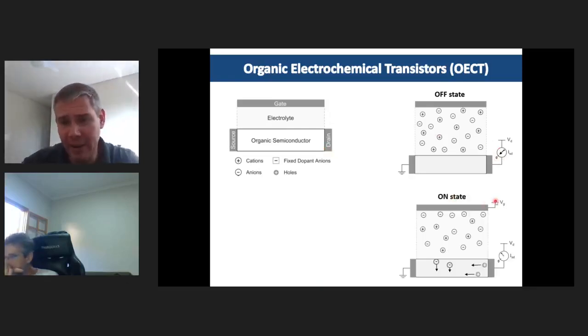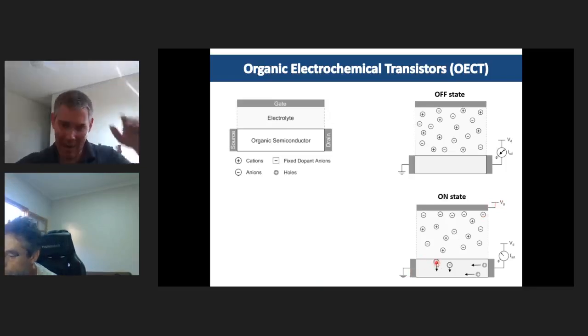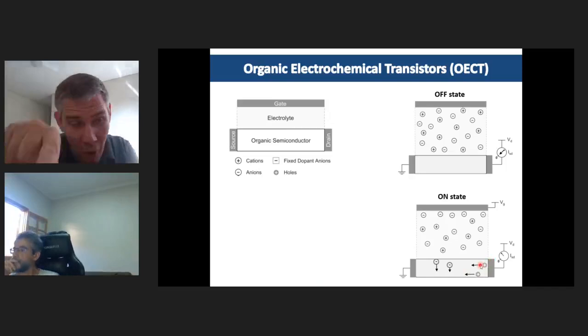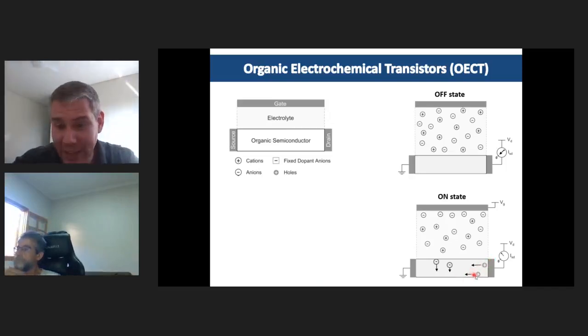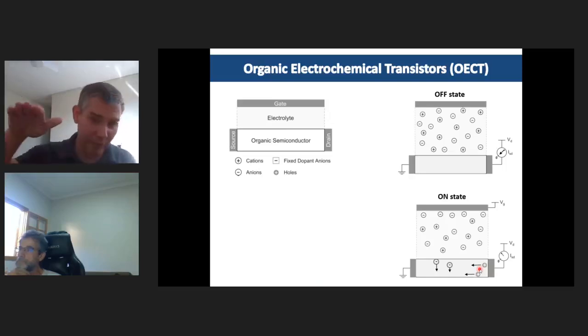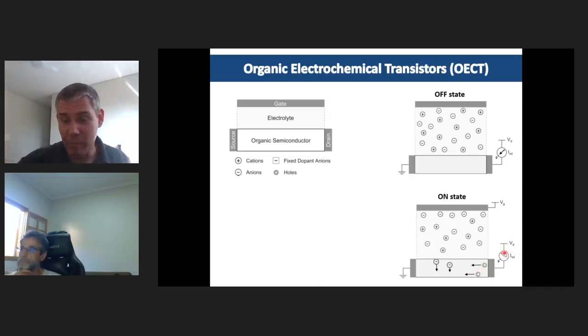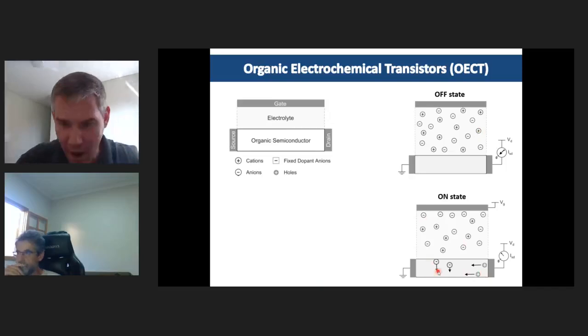But as you go to the on state, and here I'm applying a negative bias to the gate voltage in relation to the source, I push anions into the material. And to maintain neutrality of the semiconductor within the channel, the drain injects holes, or extracts electrons, right, to maintain neutrality. And by injecting those charges to compensate the ionic species that are entering into the semiconductor, you increase the amount of charge, and therefore you increase conductivity, and therefore you increase the current that you measure across the channel. So it's very easy to see how doping, or how the movement of ions into the polymer, activates or deactivates the conductivity of the channel.